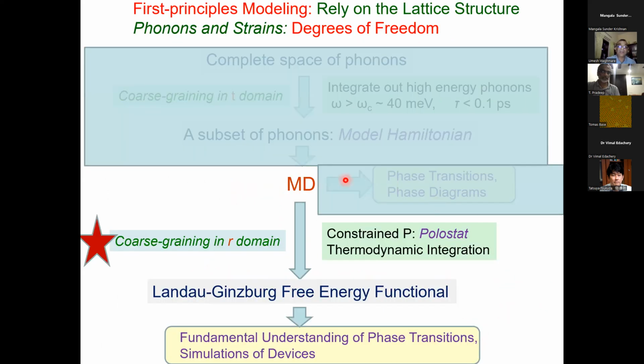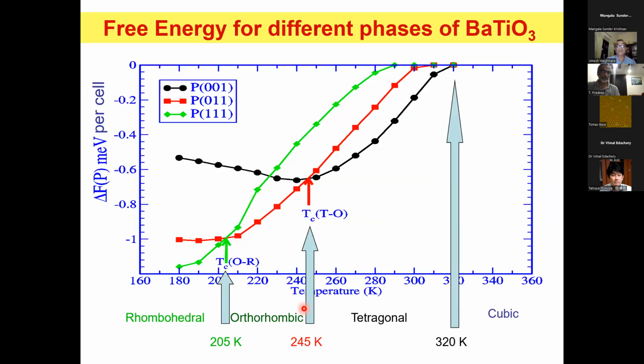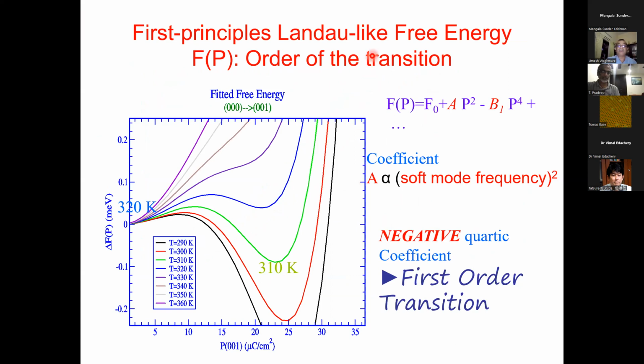Next, we will show you that we do the coarse graining in the real space domain and derive a Landau functional, and that allows us to again reproduce the phase transition. So these are free energy changes with respect to the cubic phase. The zero line is the cubic phase, and you will see we get the sequence of phase transitions from cubic to tetragonal to orthorhombic to rhombohedral. Clearly, these are first order phase transitions, absolutely consistent with experiment, and we even have access to the free energy differences. And using this, we can develop a Landau theory, and that allows us to tell what is the origin of the first order character of the phase transition.